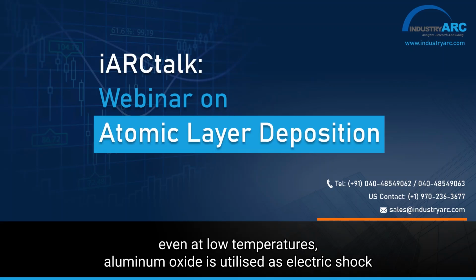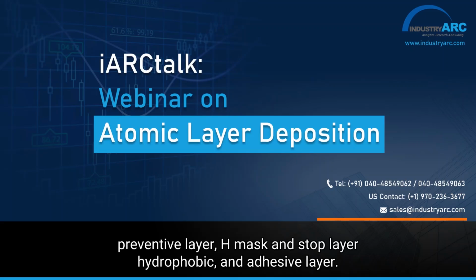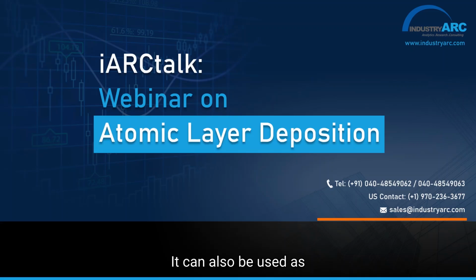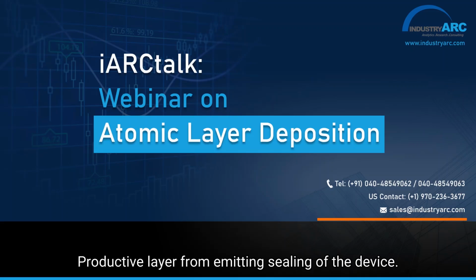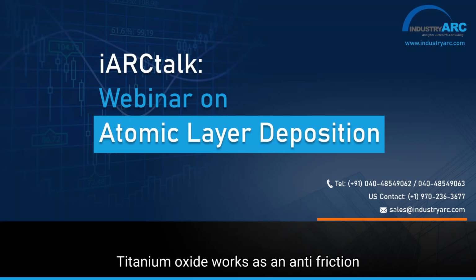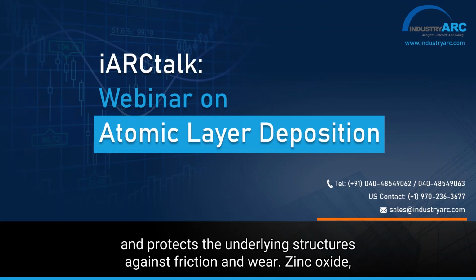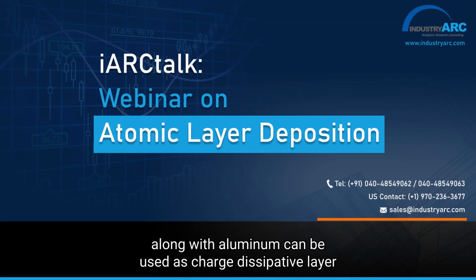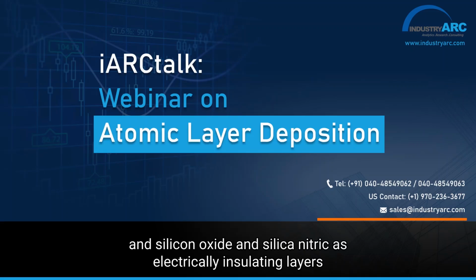Aluminium oxide is utilized as an electric shock preventive layer, etch mask, and stop layer, hydrophobic and adhesive. It can also be used as a protective layer for hermetic sealing of the device. Titanium oxide works as an anti-friction layer and protects the underlying structures against friction and wear. Zinc oxide along with aluminium can be used as a charge dissipative layer, and silicon oxide and silicon nitride as electrically insulating layers.